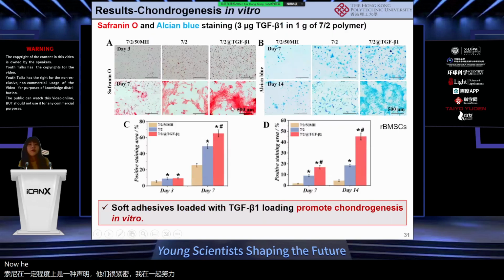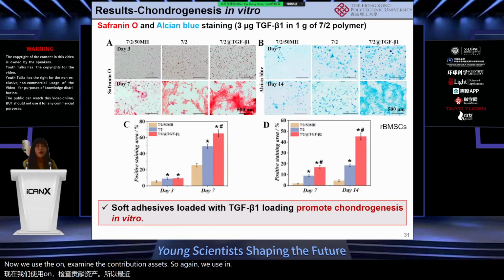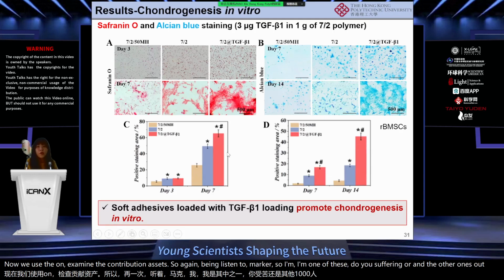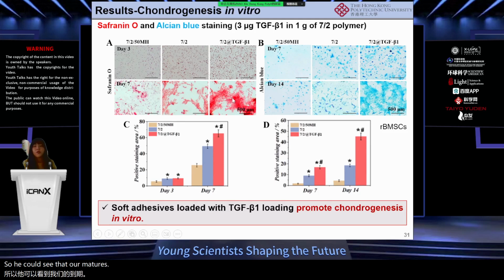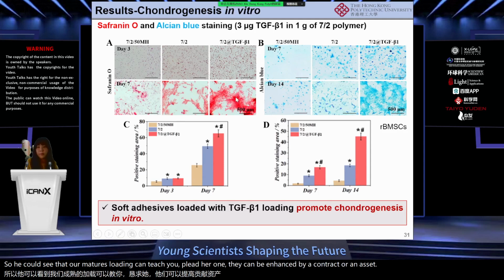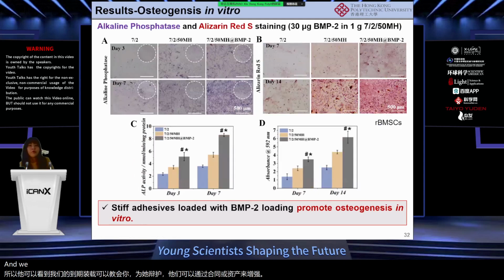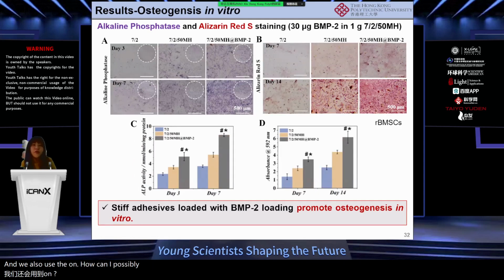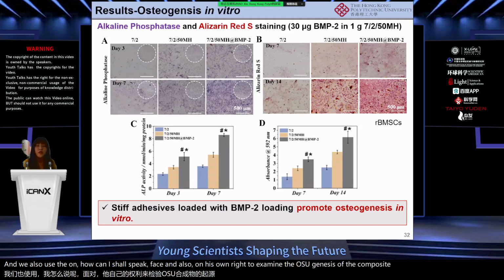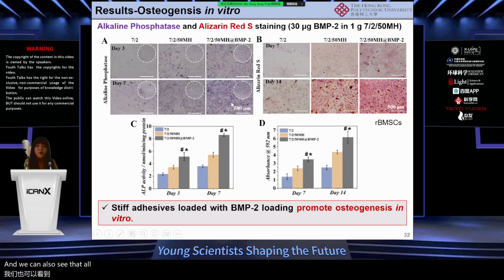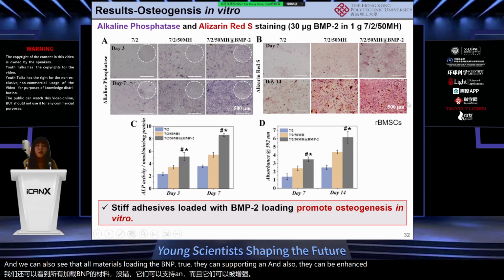And then we examine the chondrogenesis. So again, we're using two markers. One is Safranin O, and the other one is Alcian blue. So we can see that our materials loading TGF beta 1 can enhance the chondrogenesis. And we also use the alkaline phosphatase and also alizarin red to examine the osteogenesis of the composite. And we can also see that our materials loading the BMP2 can support and also enhance the osteogenesis.